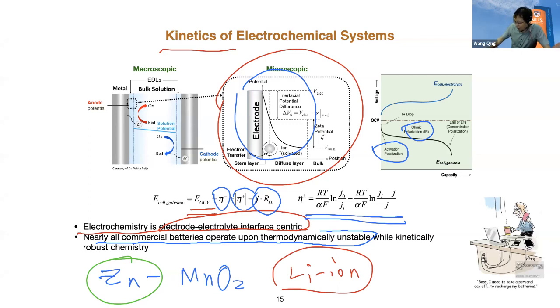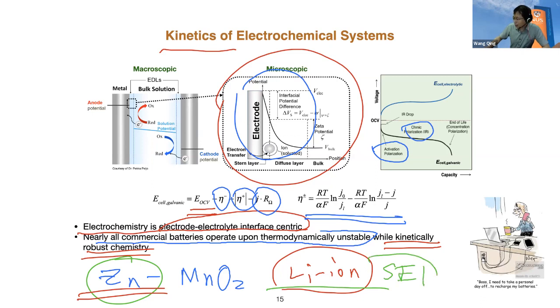But fortunately, the kinetics comes in. The kinetics can make the device work, although thermodynamically they're not stable. Like the zinc, we can suppress the hydrogen formation and stabilize the zinc. You can slow down this reaction for the lifetime of the dry cell, so we can still make it work. And for the lithium battery, if you are familiar with the battery chemistry, we know a very important thing is the SEI. This SEI layer forms on the surface of the electrode, and the SEI is insulating to electrons but conducts lithium ions, so it can protect the material underneath. So the kinetics plays a very, very important role, not only for the actual operation, but also for the use of materials which are not thermodynamically stable. Okay.